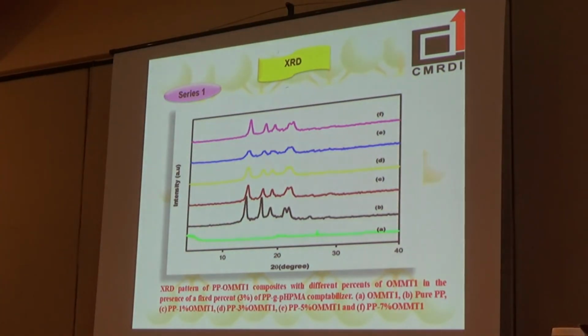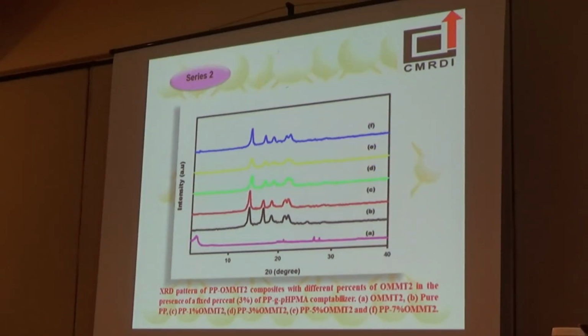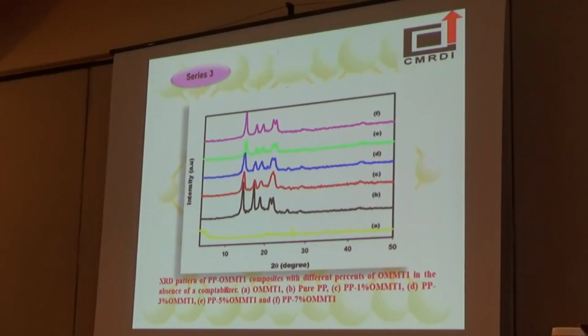XRD results show that for polypropylene organically modified clay 1 samples, the diffraction peak of the organically modified clay disappears from all the composite samples, which means that the clay lost its order and doesn't give any peak. This ensures that the obtained structure is an exfoliated structure. The same is true for polypropylene organically modified clay 2 samples, also in presence of compatibilizer. Also, in absence of compatibilizer, the trend is the same.